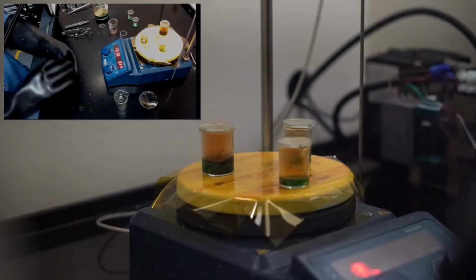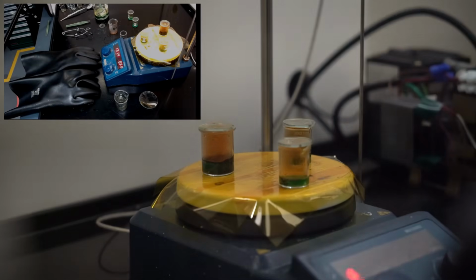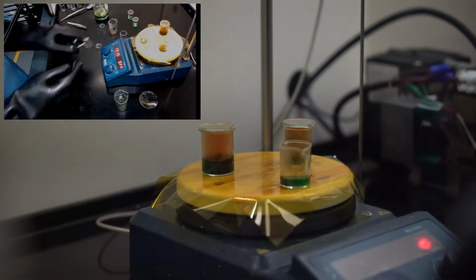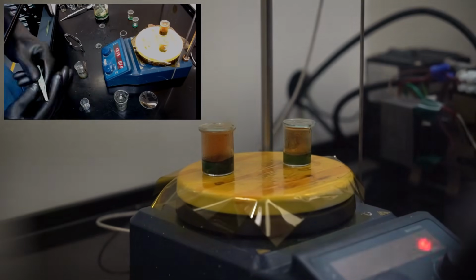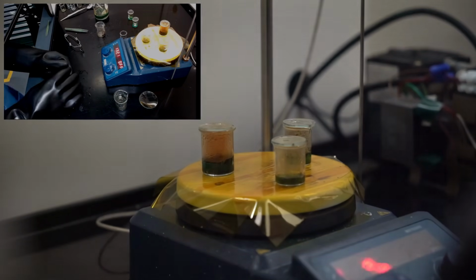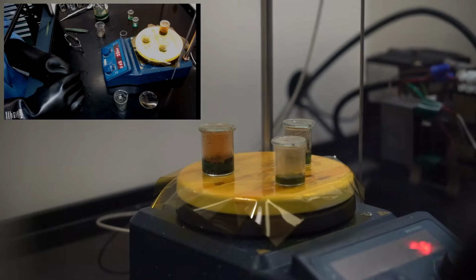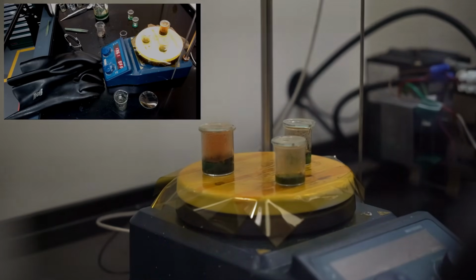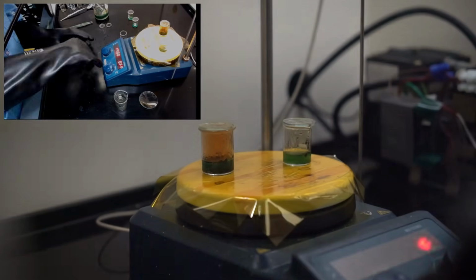And then when I've determined that the sample is done, I'll pour the waste back into the waste beaker that you'll see at the very top of the frame in the inset and let it react with some sodium carbonate that I have sitting there. The goal here is twofold. First of all, neutralize any residual acid in the waste. I tend to keep my waste around for a while because I don't generate a whole lot of it, and it's not worth making the trip to a disposal site just to drop off a few milliliters of it. So I want it to be in an essentially shelf-stable form that I can keep around for a couple of months before it's time to make the trip to get rid of it in a safe way.